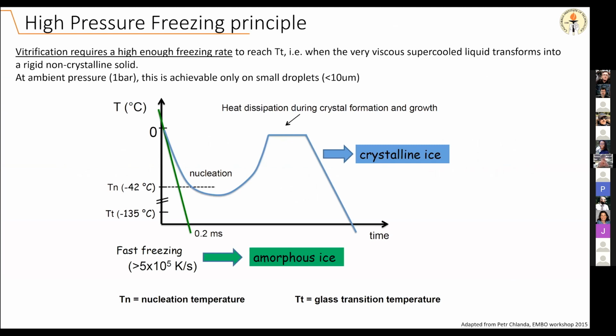So first, I want to very quickly go over what exactly we need to achieve when we're trying to vitrify our sample. When we're vitrifying our sample, we need to freeze it with a high enough freezing rate so that we reach the glass transition temperature without leaving the time to the water molecules to rearrange into a crystal. And so this can be done on very thin samples at ambient pressure, which is why it's applicable on thin cells and thin and small proteins.